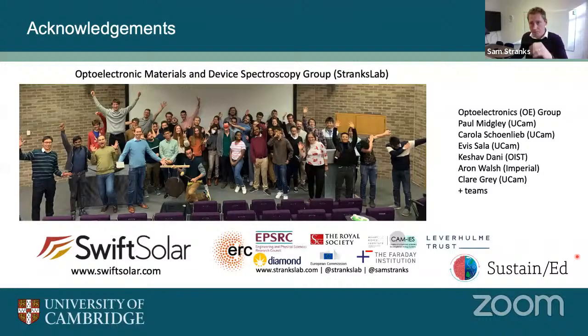Okay, so I think we're running out of time. Maybe I'll take one last question. There's a question on what are the mitigation approaches to have stable perovskite devices? Very good question. This is when we're thinking about stabilizing the absorber layer. If you remember, I showed some of these small impurities that are really problematic. There are some very promising additives and passivation approaches that can mitigate defects. These are chemicals that we can add that either convert these unwanted phases to other things, or that can interact with these iodide interstitials and make them benign. These seem to be a very promising way to get rid of these traps, but also stabilize these cells as well.